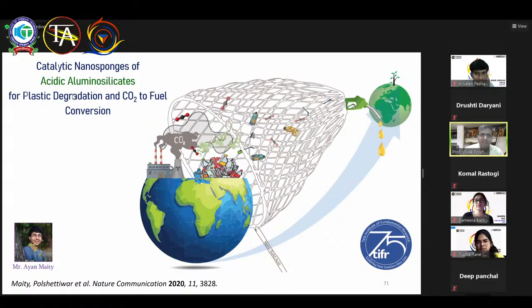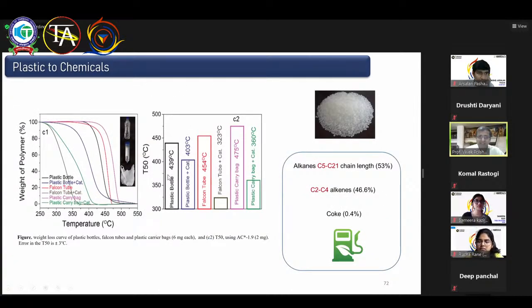So we wanted to have a solid acid which has bigger pores, bigger holes, so that the bigger polymer molecule can diffuse in, and stronger acidity. And that's the material that we recently developed. We call it acidic aluminosilicate, which has mesopores and acidity like a zeolite. And that allowed us to degrade the plastic to the chemicals. We were able to reduce the degradation temperature from, say, 450 to around 350 degrees Celsius, a 100-degree decrease, which is again at a research level a good start. But this is not what is required to make the process sustainable. You need to really degrade the plastic at less than 100 degrees Celsius. You need to develop a catalyst which is stable, reusable, so that you can degrade the plastic even at less than 100 degrees Celsius.